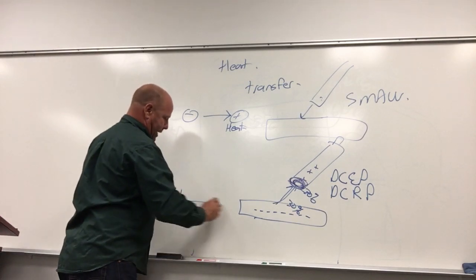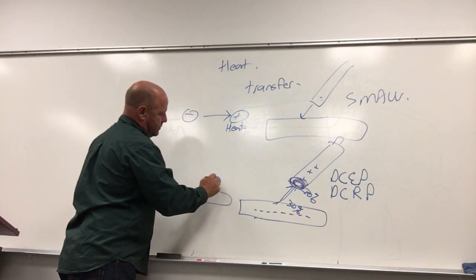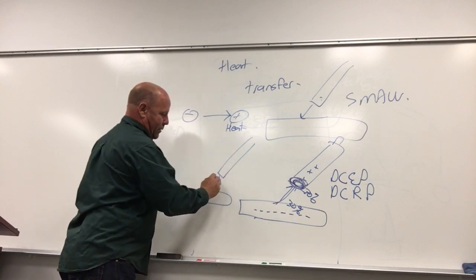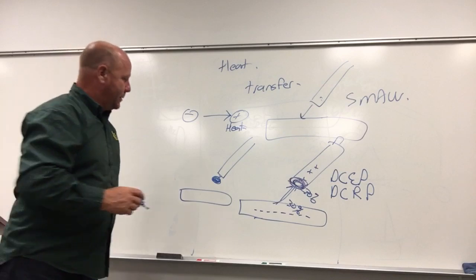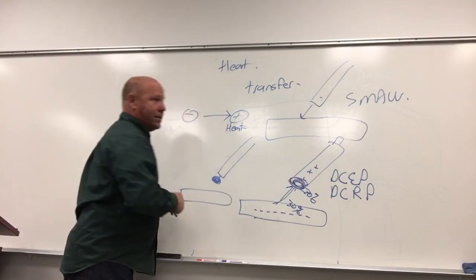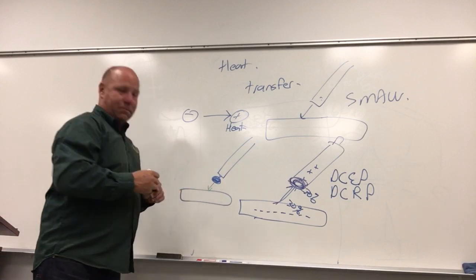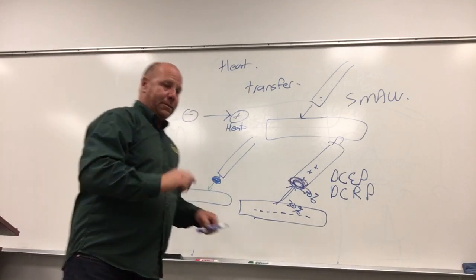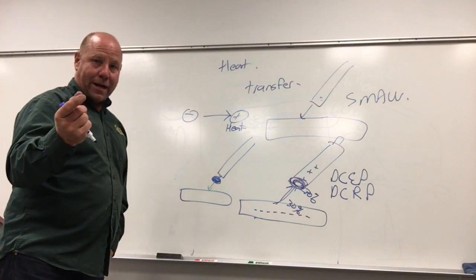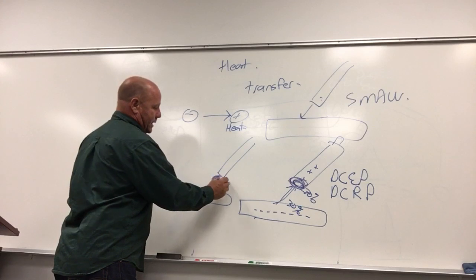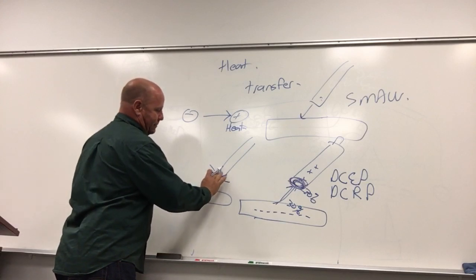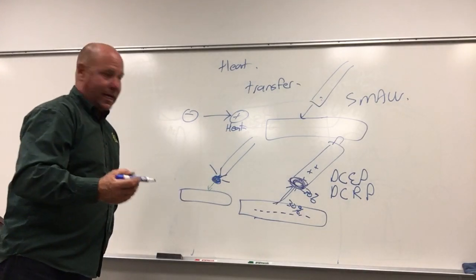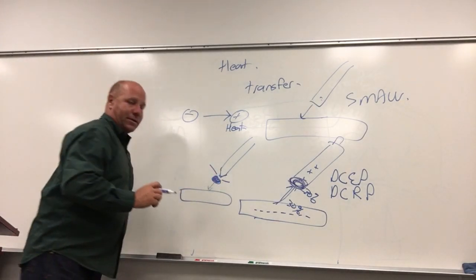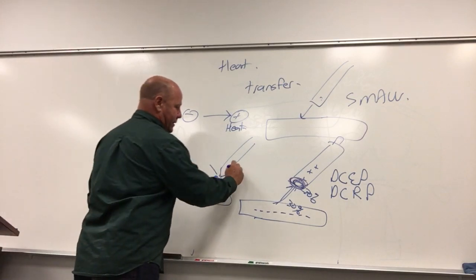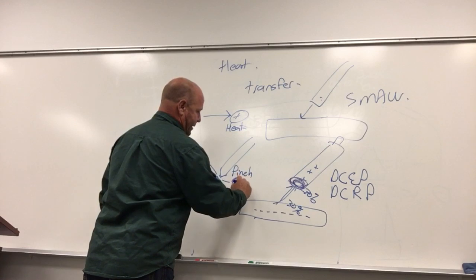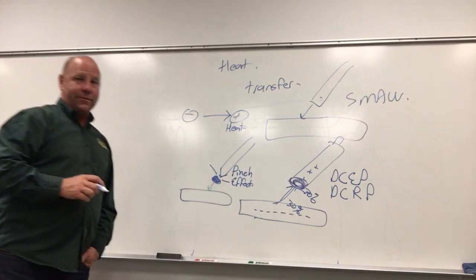The tip of this electrode then becomes a ball, and it desires to separate itself from the rest of the electrode. Magnetic forces are now pulling this electrode into the puddle. Magnetism is pulling this tip of this electrode into this puddle. As those forces bear down on this molten ball on the tip, this electrode starts to neck until it gets small enough that the magnetic force is actually strong enough to pinch off that residual little neck, and away you go. This pinching is called the pinch effect. Proper noun, so we use effect.